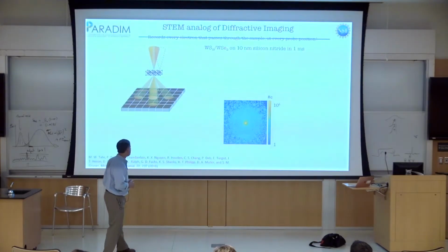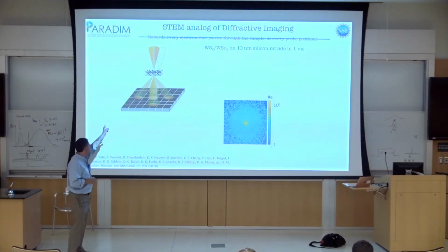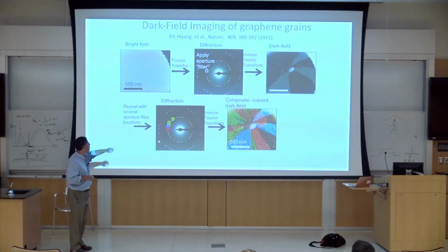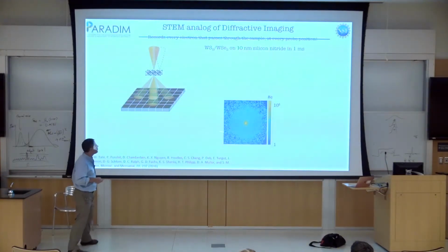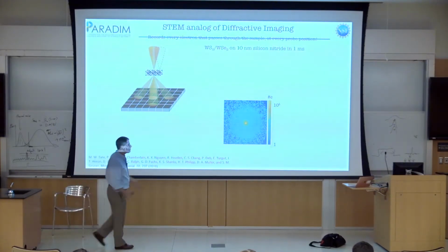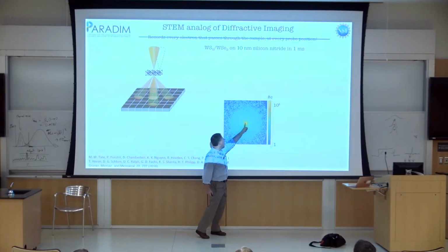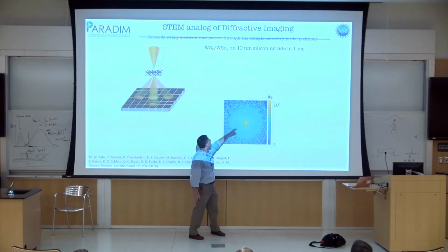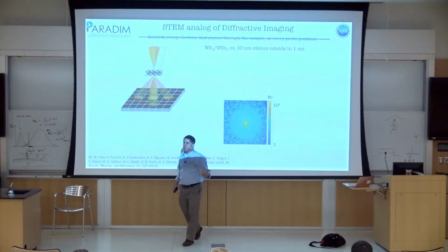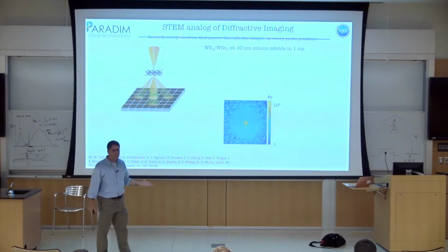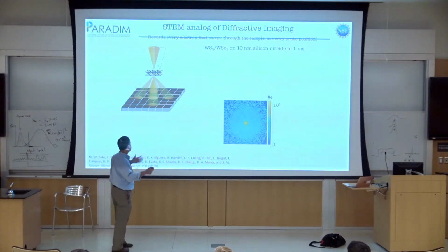So what I'm going to do is make a beam where before the sample I've set an aperture, which is basically my probe-forming aperture, which is going to basically be this thing. And that's going to give me a diffraction spot that is that wide. So I now look at this beam, and I've illuminated that range of angles. There's my diffraction. This is a monolayer of tungsten sulfide. There's my diffraction spot. So this aperture size is about 1/5 of the diffraction spacing. So I'm expecting a resolution of about 5 atoms. And that's delta K, delta X.